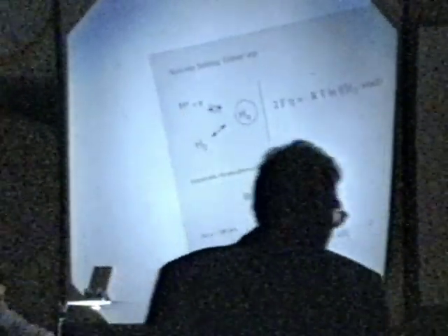These are limiting cases. Now you may say, well, this is a fairly hopeless state of affairs, we don't know very much unless we measure the loading directly. In fact, there are some simple relationships that we can derive to help us understand the situation. If we have our desirable state, our non-rate limiting Volmer step, we can write this relationship for the overvoltage and the chemical potential of the hydrogen in the voids.